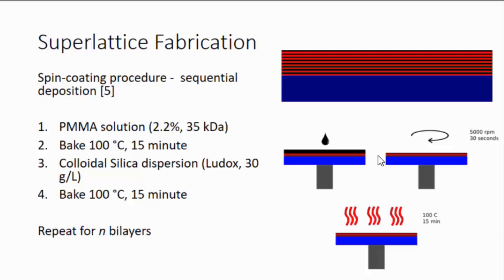Although I know I just said it's usually a very, very fine process to be able to fabricate these crystals, we have based our work and continue to work on a spin coating methodology, which has been studied before. This has shown that it's able to produce a reliable phononic bandgap and also at room temperature, which are two of the key areas which we wanted to work in. So what we did is we had a liquid phase of PMMA and we spin coated that and baked it. And then we had a colloidal nanoparticle dispersion, which we spun onto the top of that, and we just repeated that until we had the appropriate amount of layers.